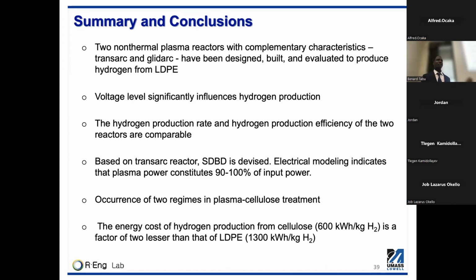Now, based on our previous studies, we devised a streamer dielectric barrier discharge, and the electrical model indicates that 90 to 100% of the power actually goes into plasma. And for the treatment of cellulose, we see the formation of two regimes: devolatilization and char reaction. And lastly, we also saw that the energy cost of production of cellulose was half that of low density polyethylene, based on its thermophysical and chemical composition, because the low density polyethylene is thermally very stable.